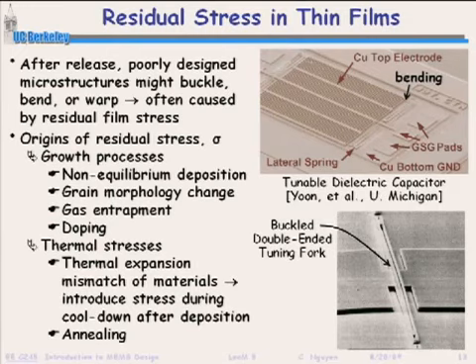Thermal stresses are another reason. So when you're depositing films at high temperature, okay, what happens? You deposit it at that high temperature. At that high temperature, everything is under no stress, right? There's zero stress. But when you take it down in temperature, what happens? Everything starts shrinking, right? If your film doesn't shrink at the same rate as your substrate, which is going to be the case if they're different materials, which is generally the case, then you've got some tension between all that, compression or tension, right? So there's stress between that, and that now can cause warpage of the wafer itself or warpage of your devices. So that's what's happening here.